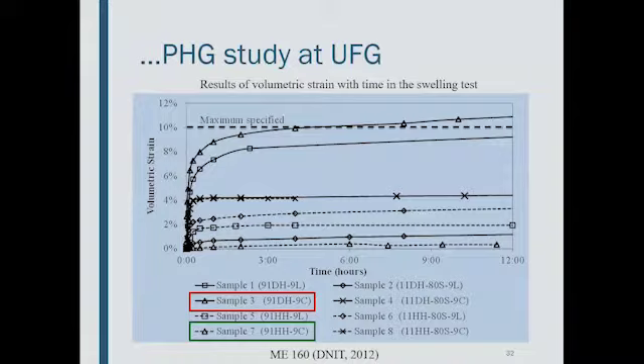It's a Brazilian specification where we put the sample in contact with water during a period and observe the volumetric strain. These results showed that mixtures with the DH type have high values for volumetric strain, but for mixtures with the hemihydrate type of phosphogypsum, you have low values. So it's a good result, showing that the transformation of the DH into the HH can work.